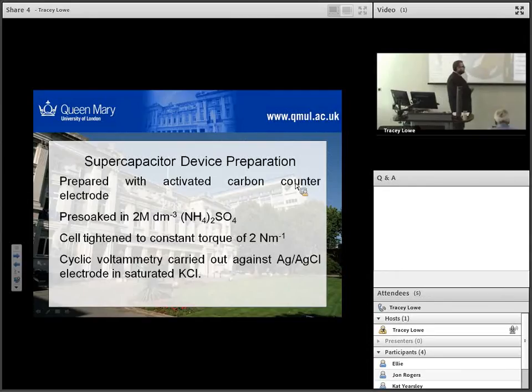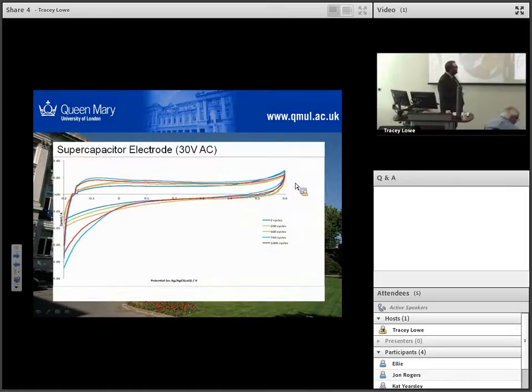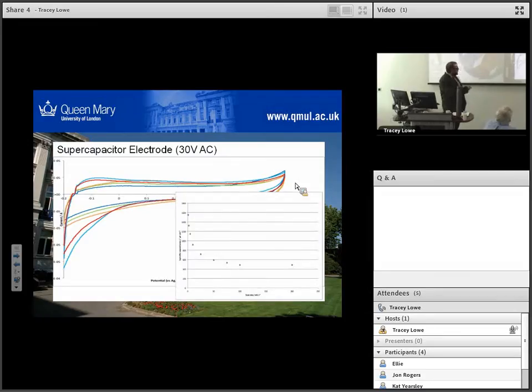Some guys at the University of Surrey actually prepared these devices and tested them for us, so I'm not going to say too much about that, but just show a bit of the testing. This is up to 1,000 cycles, and we can see these are broadly rectangular, which is the ideal capacitor behaviour. There's some evidence at the ends of cycling of some change or destruction of the electrolyte, which is why we get these large peaks - not exactly where we want to be, but still a lot better than many other things. As a result, the specific capacitance falls off, in this case going down to about 500 microfarads per square centimetre from where it started at 1600.